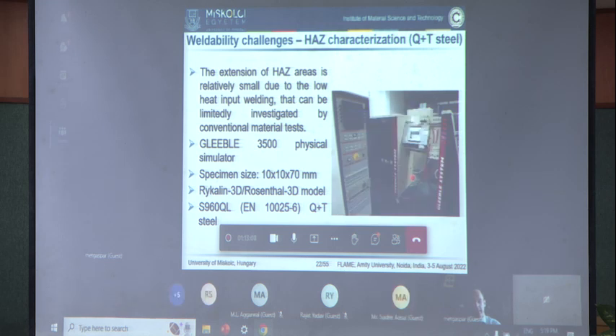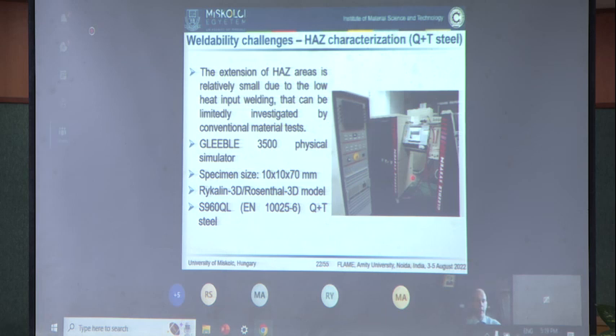Physical simulators, such as the Gleeble 3500, provide a unique solution for the production of critical heat-affected zone areas. You may know that in real welded joints, the extension of the heat-affected zone areas is relatively small due to the low heat input, and therefore they can only be investigated to a limited extent by conventional materials tests.